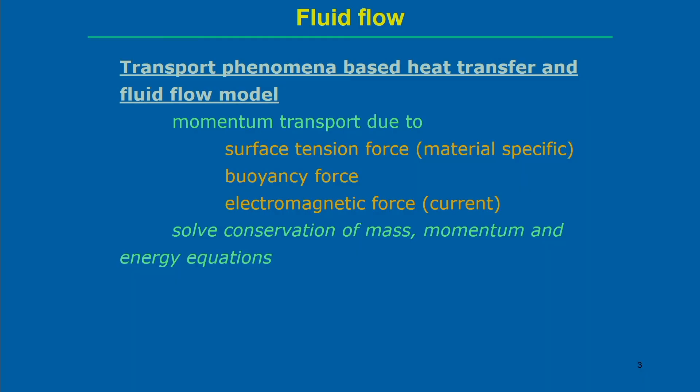Buoyancy force also acts as a driving force based on density differences within the small weld pool, but the surface tension force is more significant and more influential on the momentum transport in the welding process. In arc welding processes, there is current flow, which generates electromagnetic force that can be considered a body force or driving force for material flow. However, in laser welding we can neglect the electromagnetic force and consider only surface tension and buoyancy forces as driving forces.